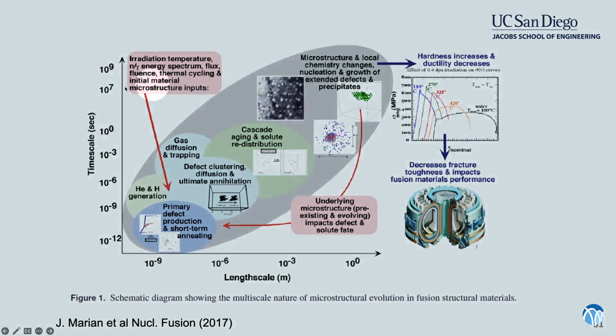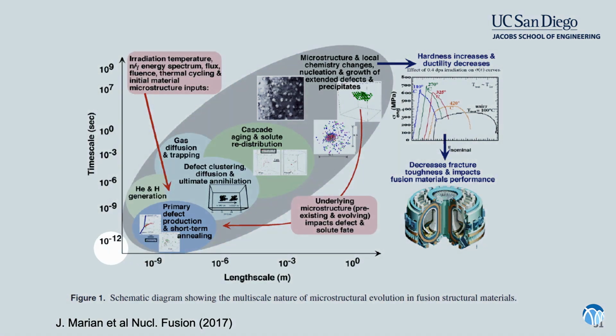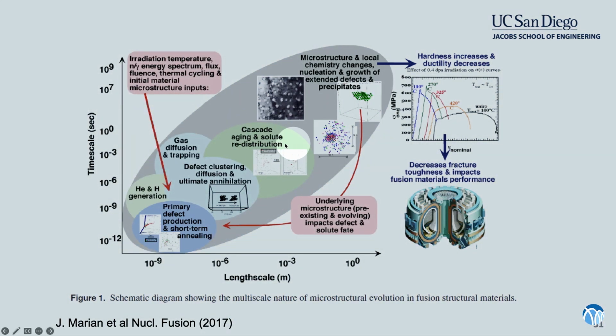On this axis here we have time scale. On this axis we have length scale. So if we start here at short times and small length scales, the first thing that happens under exposure is you start getting a lot of defects generated. As you have longer length scales and time scales, you start trapping some of that fuel, the fuel that I was talking about. Even longer length scales and time scales, you start having major changes to the microstructure.